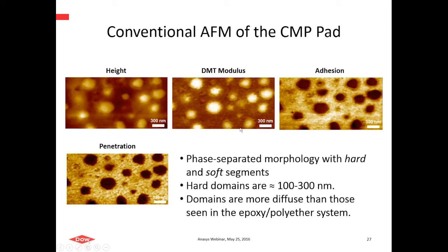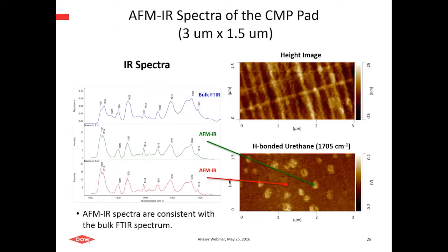So we again easily resolve this mechanically, and let's look at what we can see spectroscopically. In this case, here's the bulk IR, and you have AFM-IR in a couple of different locations. You can see we've got very similar infrared spectra, at least at first glance, pretty much anywhere we look. And in this case it's a little bit more challenging. The compositional variation is a lot more subtle in this system. So here we're actually going after variations in relative band intensities as a function of position, not necessarily nice separate and discrete absorbances that resolve in the morphology. But you can see, again, it reinforces the fact that the AFM-IR spectra look a lot like the bulk. You see that here very nicely.